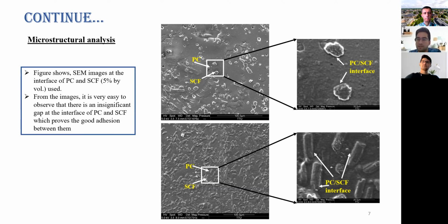So we do the microstructure analysis using SEM. As you can see in the figures, I did the microstructure analysis for the polycarbonate and the short carbon fibers. As you can see, there are insignificant gaps at the interface of the polycarbonate and the short carbon fibers. That means these two materials are well compatible with each other, and we can use this composite filament for building any automobile part or any part related to any industry. Okay, so we verified that. This is one of the steps we have to follow all the time.